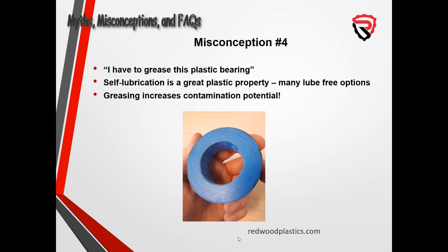So grease can carry in grit, sand, any sort of contamination, and plastics, because they're obviously softer than metal, on that contamination can do more damage. So greasing can sometimes hurt from a contamination perspective. And my last point is many, many plastics with all different price points are available in oil or solid lubricant filled. So if you don't want to grease at all, if you don't want to do maintenance at all on the plastic, we can really help you out, and it's not difficult. So my point here is trust the plastic and trust the lubricated grades of plastic to do the lubrication. You don't need to stuff it full of grease.